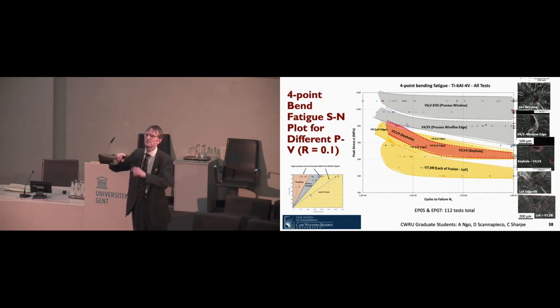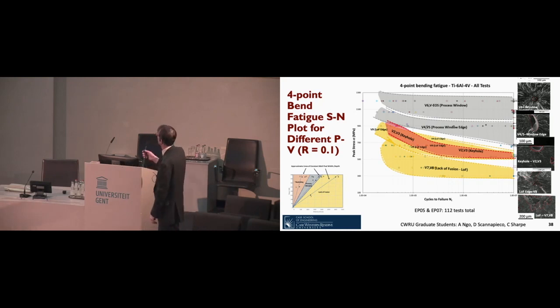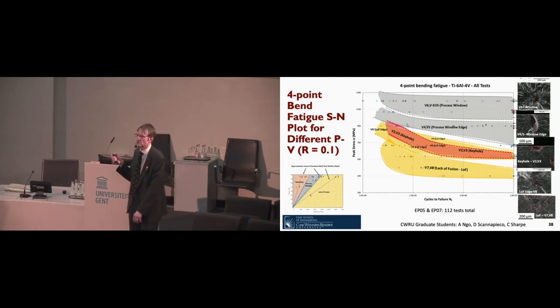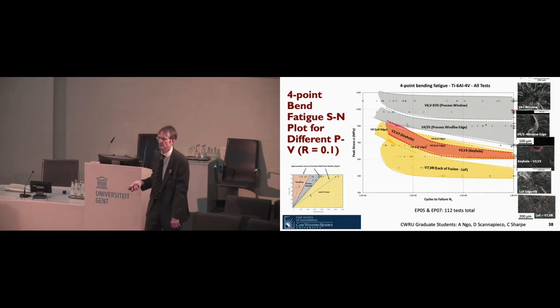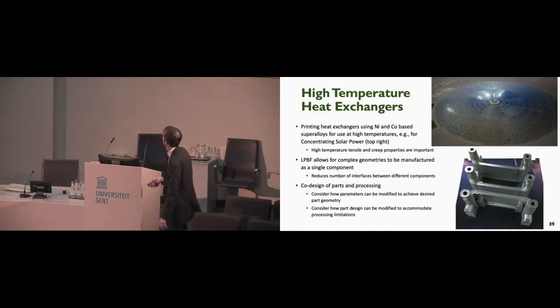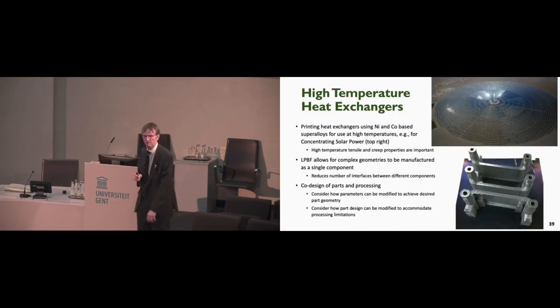But that's because four-point bend fatigue stresses a much smaller volume than does regular push-pull. So there's a correction to be made for that. But the basic message here is if you print properly, then you get equally good results as you do for wrought material. And moreover, you can even find examples of cracks starting not from a pore, not from a defect, but from something in the microstructure. So there's that tantalizing prospect that we can print things so well that we no longer have to worry primarily about the defect structure. Okay, so now I'm going to change gears on you again.